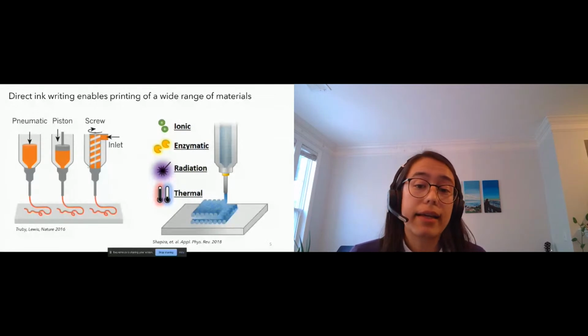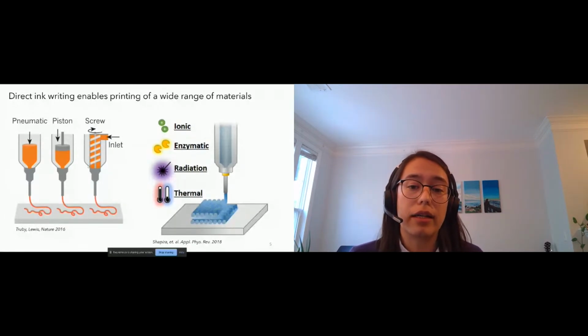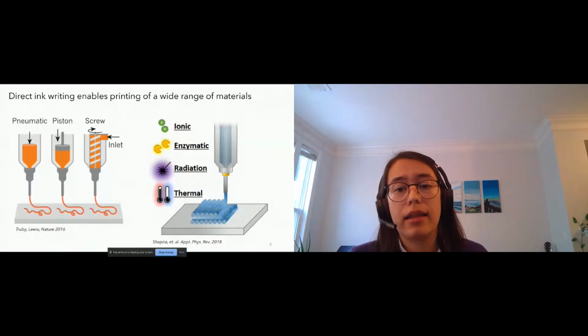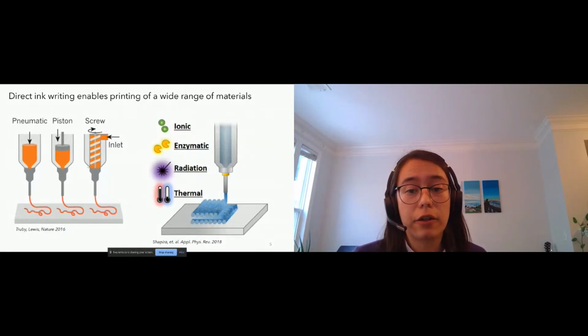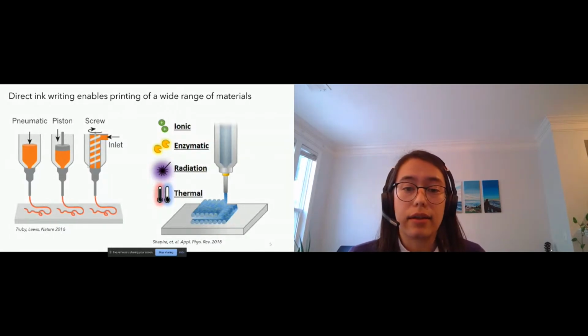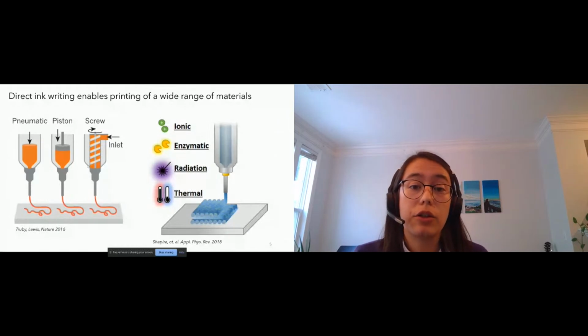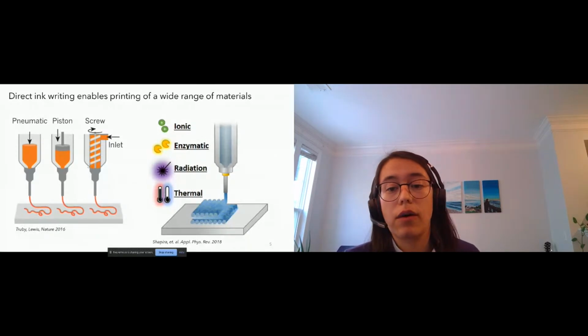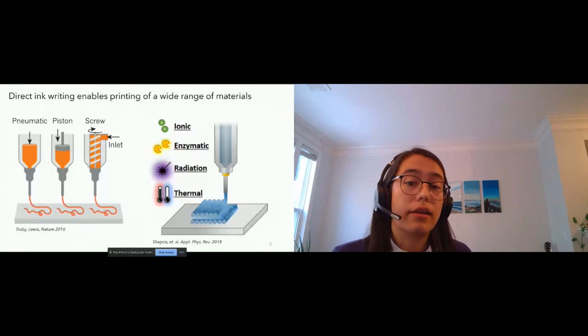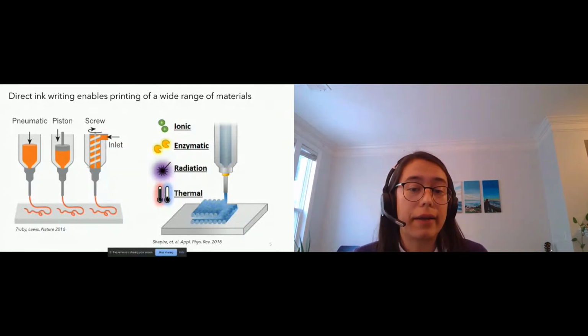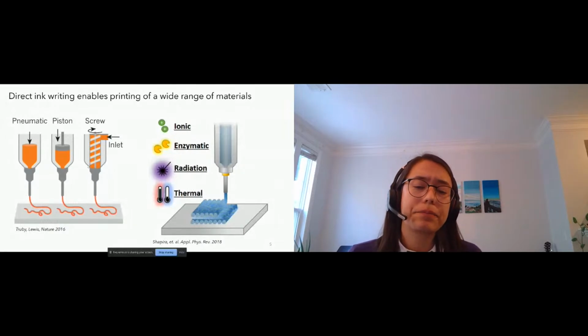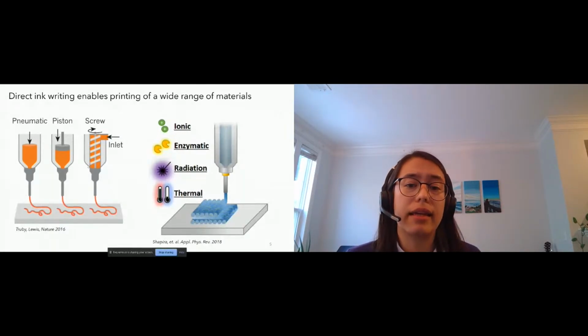If it's something like alginate, then you could submerge your part into a calcium bath for ionic cross-linking. If you have certain biopolymers, then you could use enzymatic cross-linking to turn that part into a solid. You could, again, use UV radiation. So all these photopolymers are then going to be printable using direct ink writing. And then there's thermal curing. If you have something like an epoxy, you could write out your part and then heat it up to cure it.